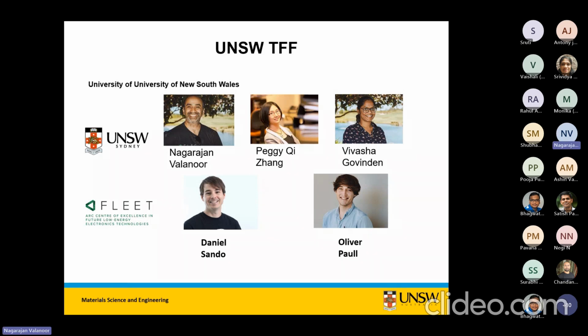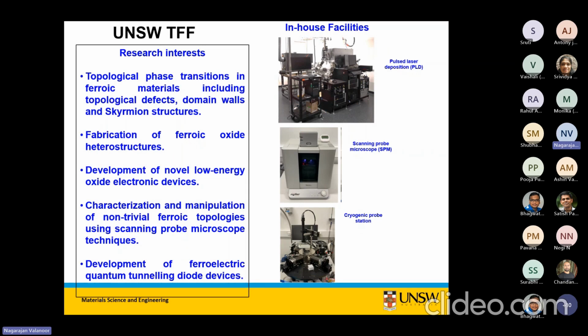So I was very impressed with SENSE and its facilities. We are not as well endowed and as rich as SENSE in any manner. So we have a couple of pulse laser deposition tools, one that is made by Neocera and the other one that is made by Pascal. Reasonably standard pulse laser deposition tools, except that in one of the Neocera chambers, the target to substrate distance is quite large. Normally, when you design PLD chambers, it's 5 to 7 centimeters. We have it almost between 12, and we can go up to 15 as well. But for most of our depositions, it is between 10 and 12 centimeters.